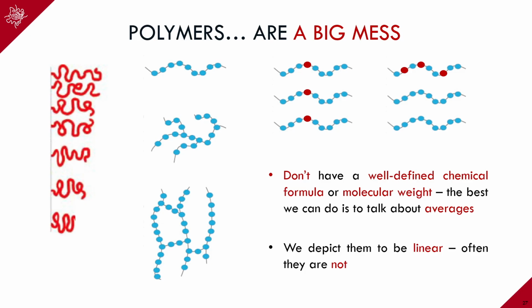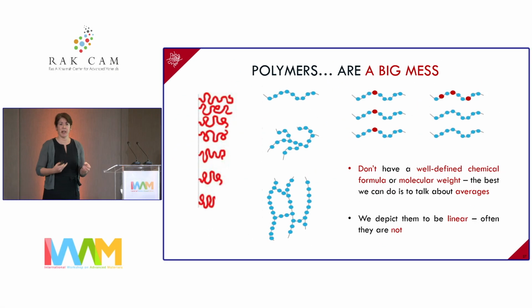But what you have to remember is that when they're drawing a polymer, we're not dealing with single molecular weight species. There's a range of molecular weights that we're dealing with. Even though we often draw the polymer chain to be linear, actually our chemistry is not that good. In reality, within the linear mixture, you might have some branches, you might have some cross-linked structures, but we can't really tell too much from the characterization tools that we have.